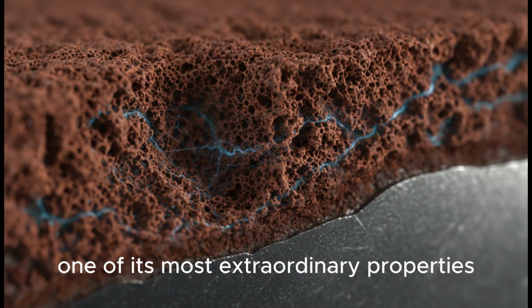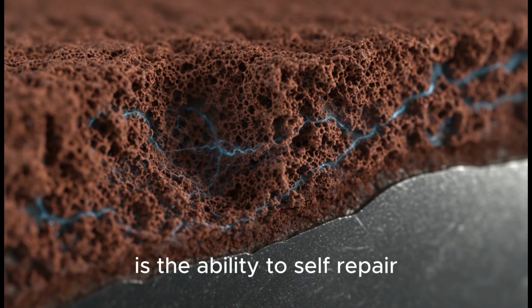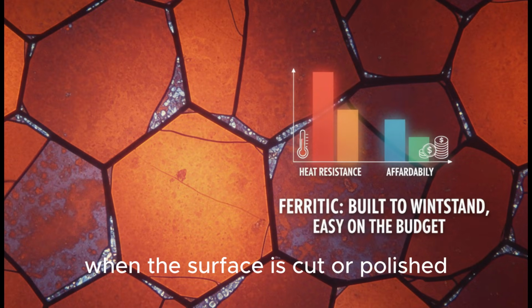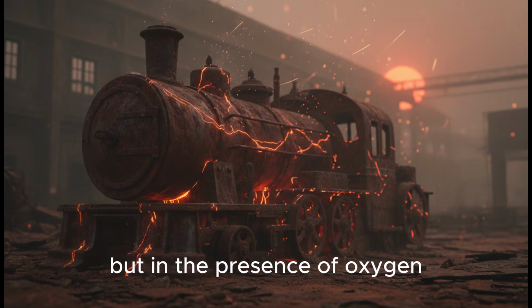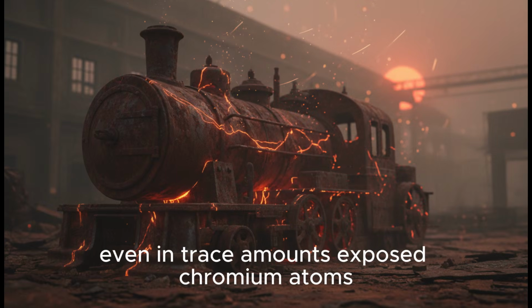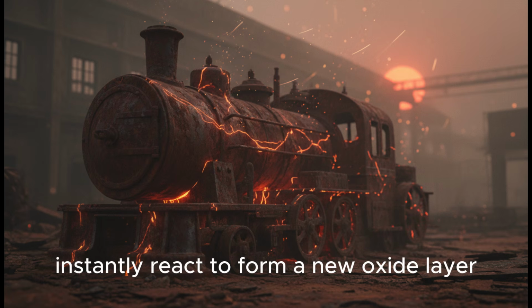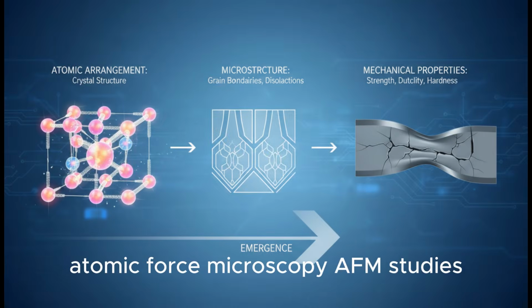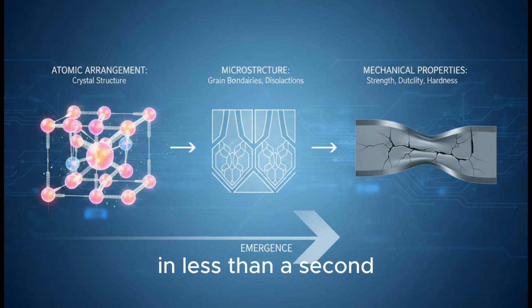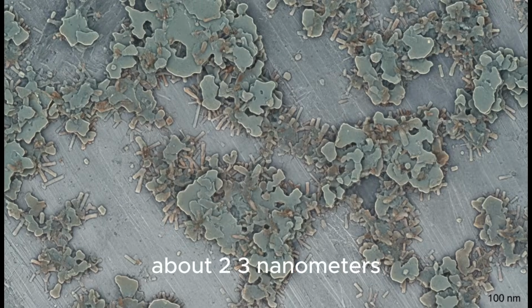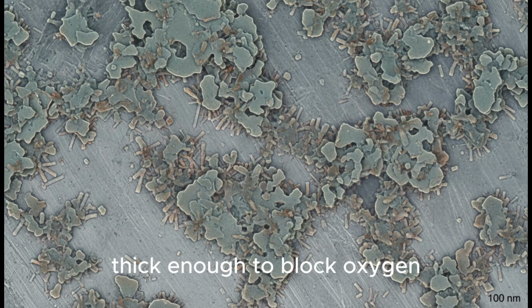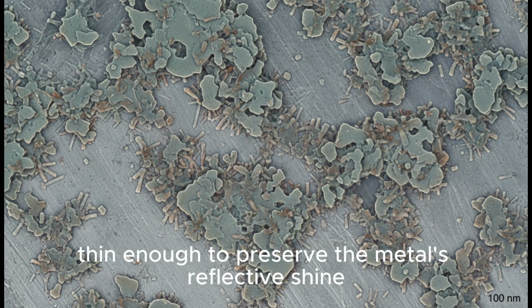One of its most extraordinary properties is the ability to self-repair without external energy. When the surface is cut or polished, the Cr2O3 film breaks. But in the presence of oxygen, even in trace amounts, exposed chromium atoms instantly react to form a new oxide layer. Atomic force microscopy, AFM, studies show that this regeneration occurs in less than a second and stops once the film reaches a stable thickness of about 2-3 nanometers. This is the optimal balance, thick enough to block oxygen, yet thin enough to preserve the metal's reflective shine.